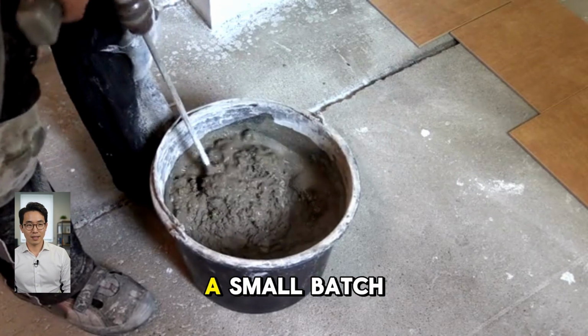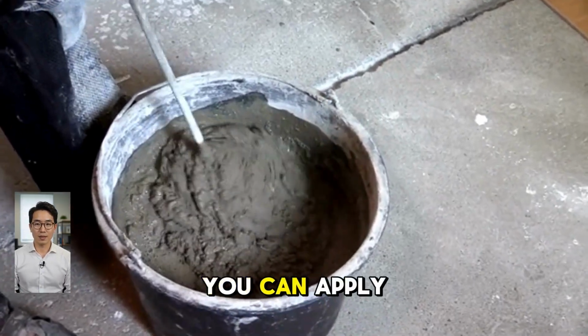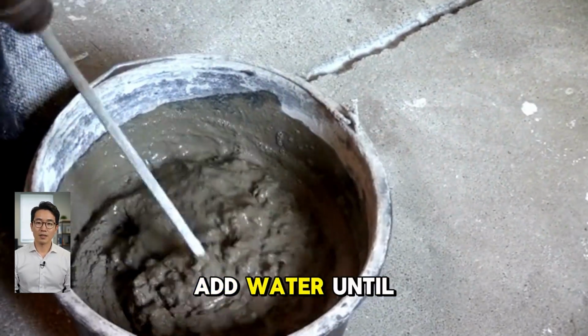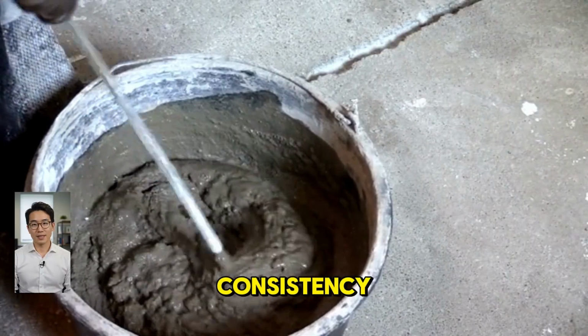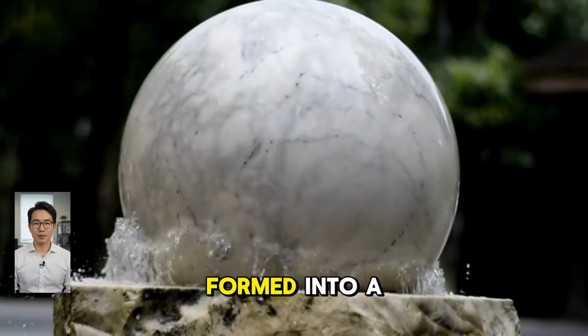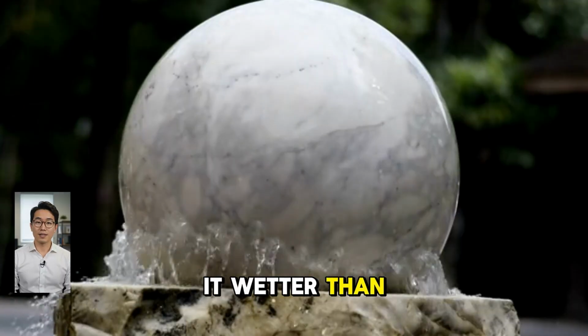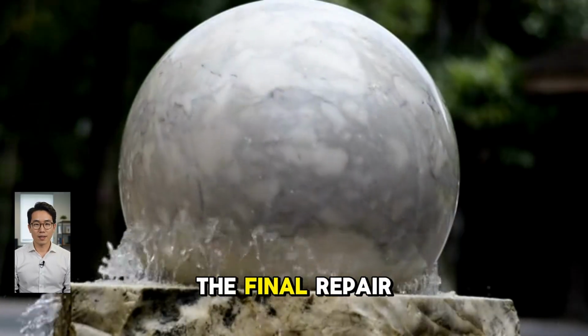Step 3, mix a small batch. Mix only the amount you can apply in 90 seconds. Add water until you achieve a stiff putty consistency. The mix should hold its shape when formed into a ball. Do not make it wetter than this. Excess water weakens the final repair strength.